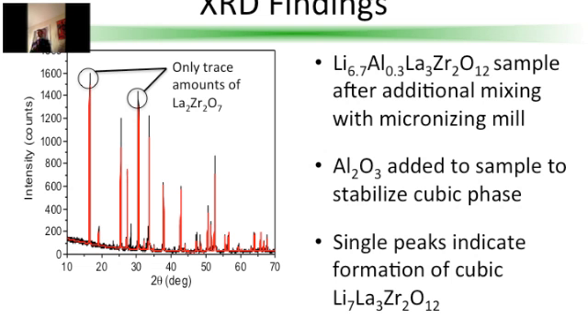Well, it turns out that if you just add aluminum to the sample, it will only substitute some of the lithium sites. So for the purposes of my research, it was perfectly fine to do so. So I added aluminum oxide to the samples, as many of the literature reported, and indeed I was able to obtain the cubic form of lithium lanthanum aluminum zirconate.